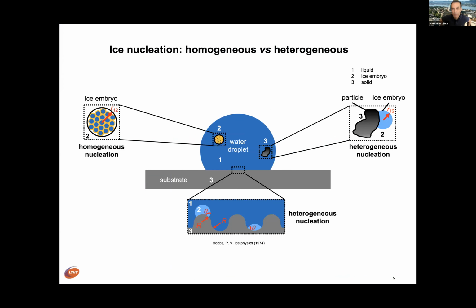And I'm going to start with, I did see that about 60% of the audience have a background in the general area, but some 40%, that is significant, do not. So it is a good idea to give a little background on what we mean about nucleation and ice nucleation, with the simplest system possible, really, which is a droplet, as you see here, sitting on a surface. And as the temperature is decreased, goes to 0, even below 0, then of course one can observe the tendency of water molecules to form ice, small crystals, embryos, or embryons, depending on your preference.